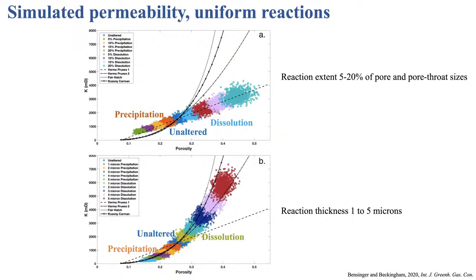The pore network model simulations using the unaltered pore and pore throat size distributions are shown in blue. And then we have dissolution scenarios and precipitation scenarios. In this top plot, we have uniform reactions that alter pores and pore throats by some extent relative to their initial size. And on the bottom, the reactions occur as uniform thickness coatings on all pores and pore throats. So you can see in each of these scenarios, we have an increase in porosity and permeability with dissolution and a decrease in porosity and permeability with precipitation. The black lines on these plots are the commonly used macroscopic porosity permeability equations. And so you'll notice for these uniform reaction scenarios, they're captured pretty well by the macroscopic porosity permeability equations.